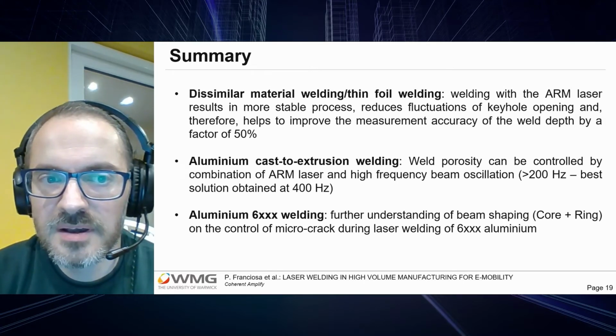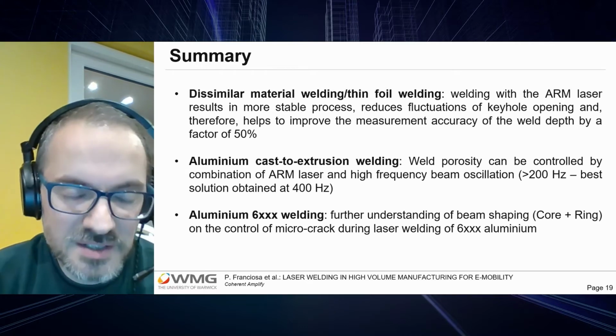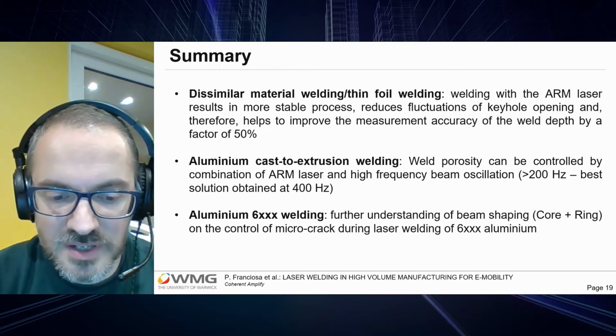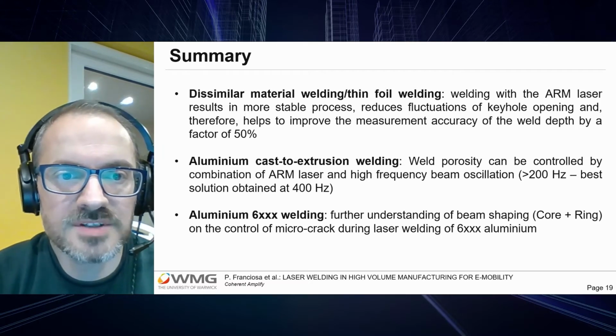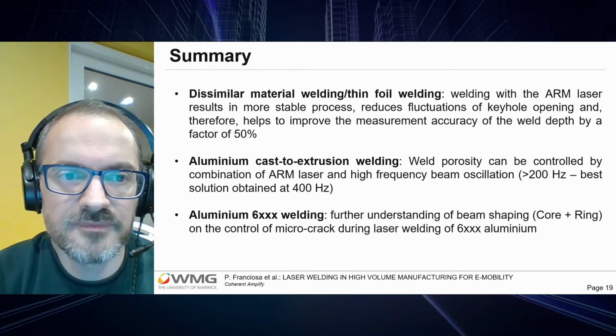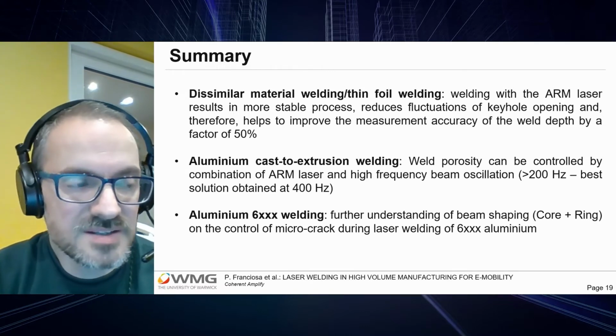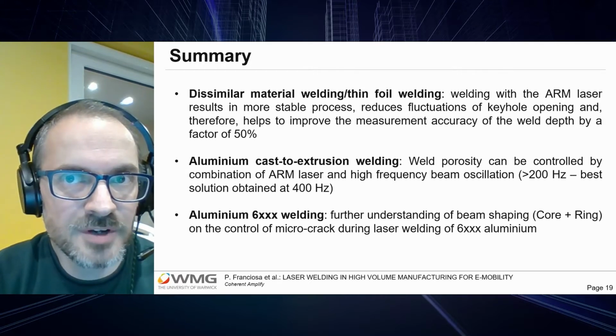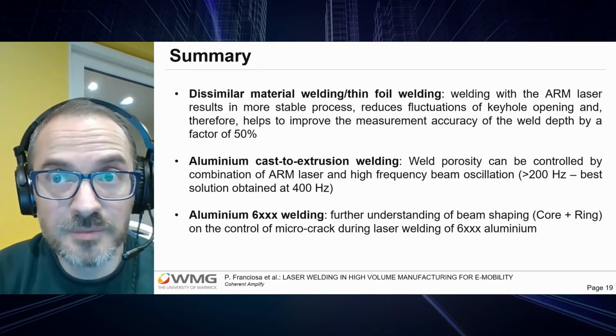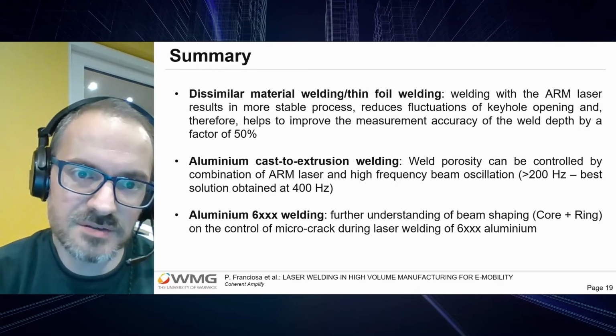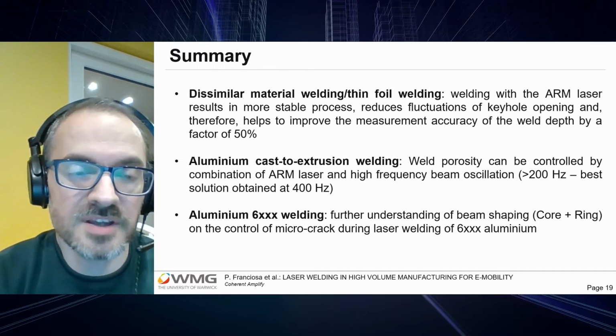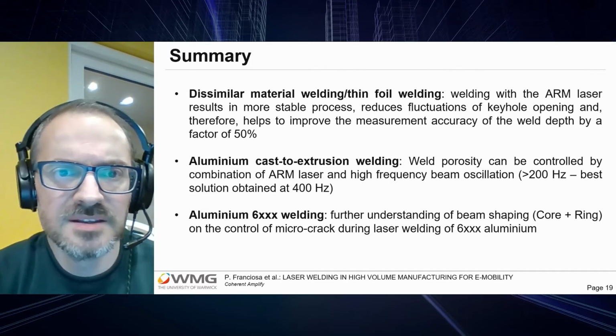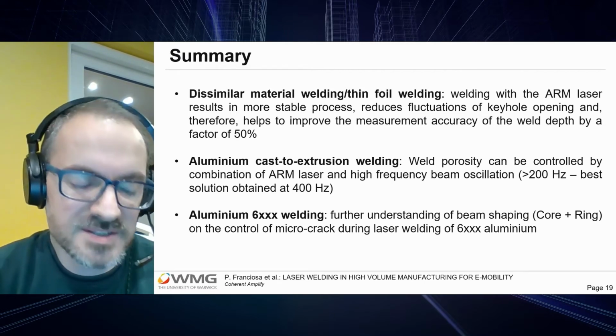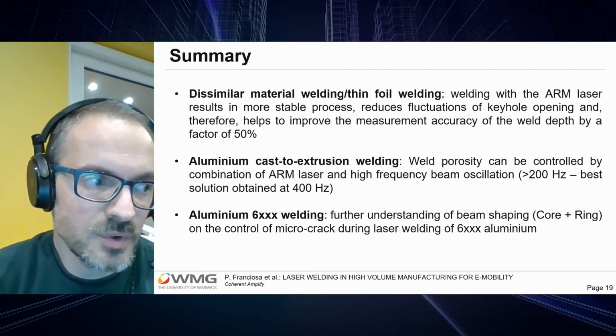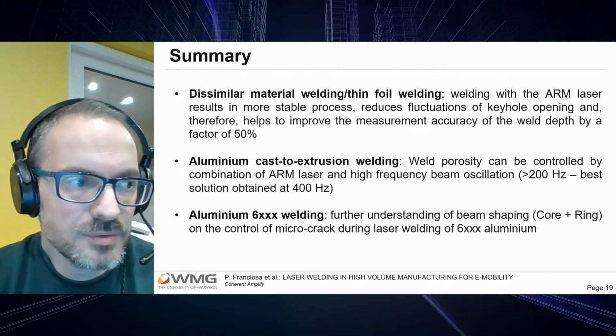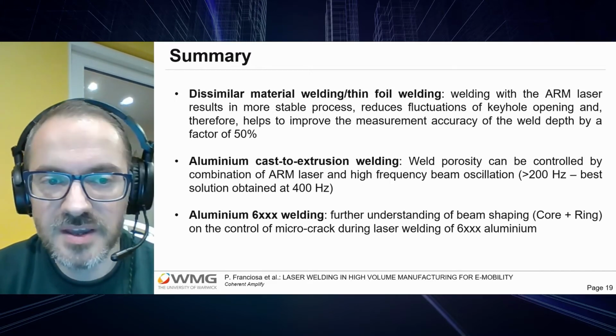The main objective was, well, we had two sub-objectives for this application. The first one was proving that using ARM laser technology we can achieve a stable process, and indeed we have seen a good result on that. But even more interesting is saying, okay, even though we have a stable process, is it possible to achieve a repeatable and accurate measurement using in-process sensors such as OCT? And this also, we achieved some promising results. The data has shown an improvement of 50% in terms of accuracy when we use the dual beam, so core plus ring, compared to the case of only core laser.